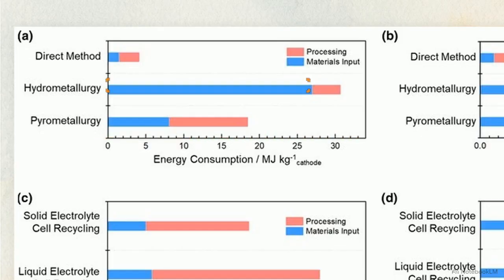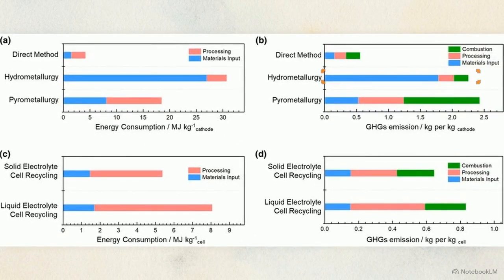To quantify the thermodynamic cost of these recycled materials, the immense blue materials input bar for hydrometallurgy dwarfs the direct method. That upstream acid production translates directly into severe greenhouse gas emissions, shown here, whereas direct solid electrolyte recovery emissions stay remarkably low. Direct recycling of solid-state batteries reduces greenhouse gas emissions by roughly 80% compared to conventional methods. It provides a thermodynamically viable path to scale these architectures globally.